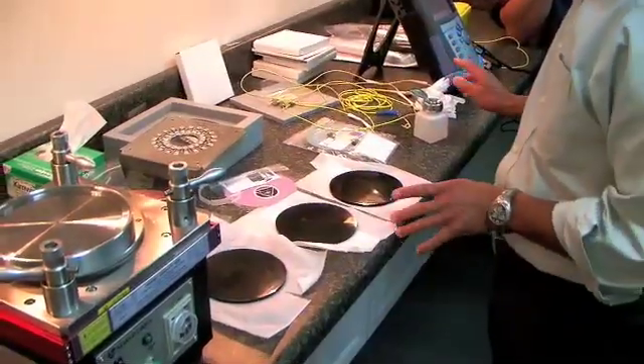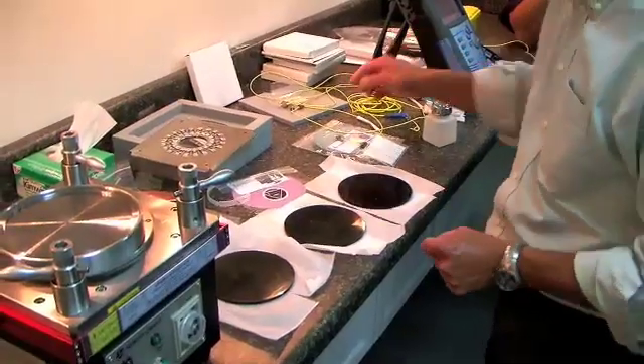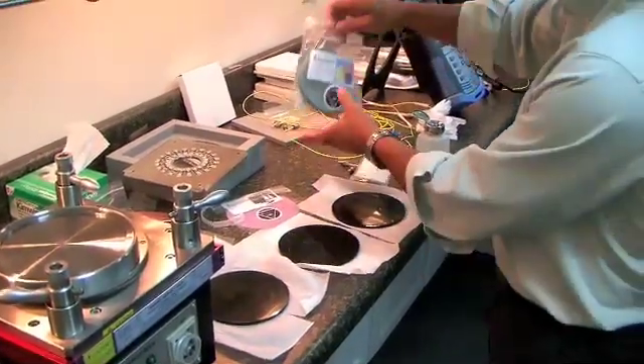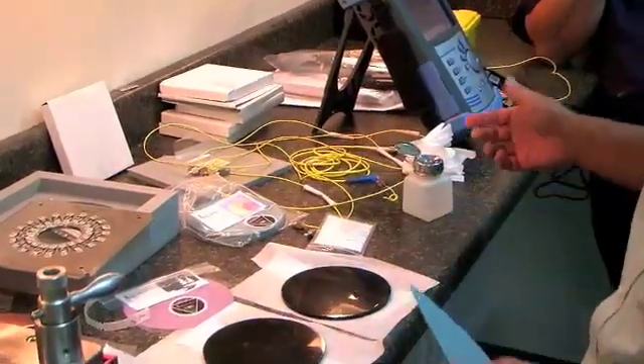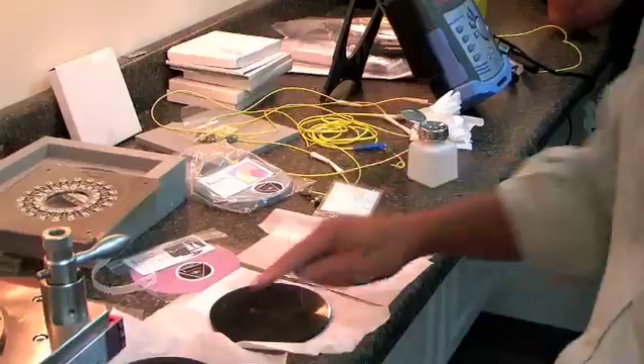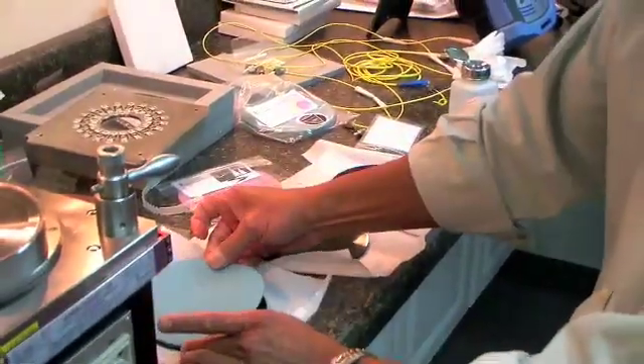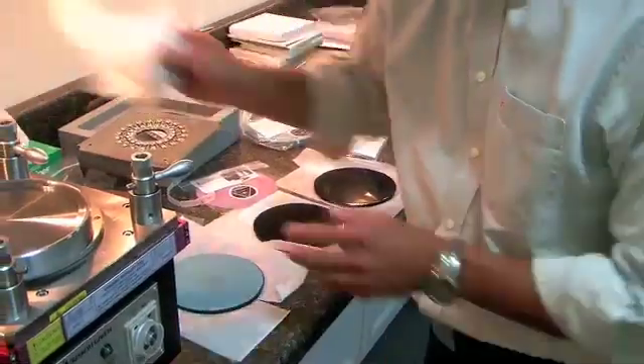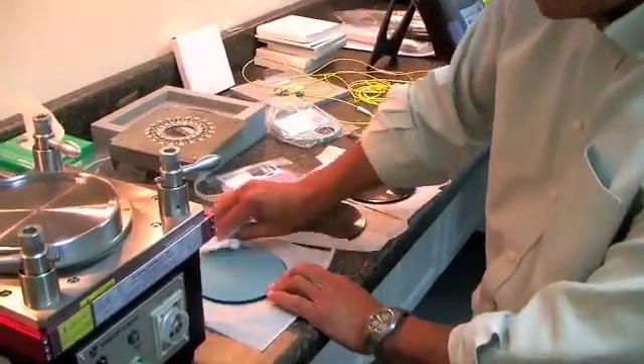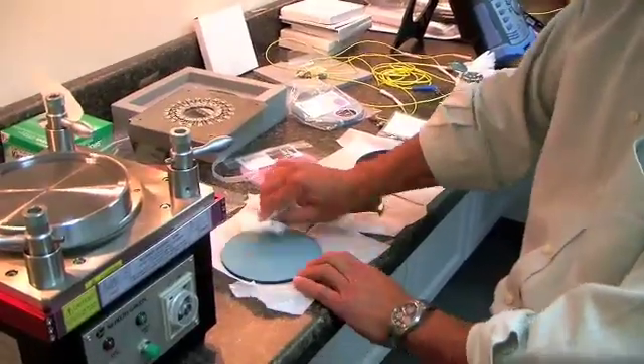A four-step process with those connectors. The first step is the same film that you did the air polish with, which is a 9 micron silicon carbide. My technique is just one little dab, drop it on the center, and then take the kim wipe and just even it out. And it will stick very good.